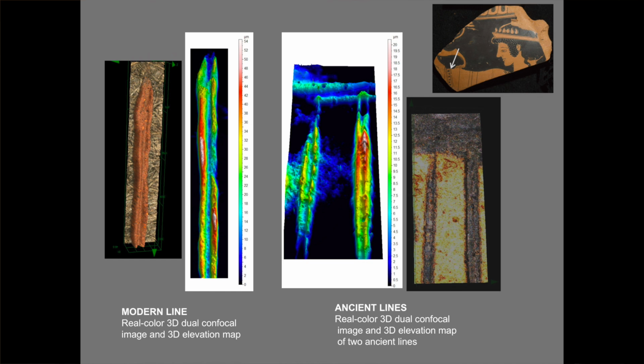I want to add that in our experiments we determined that a brush with a single hair could not have produced any of these lines because a brush of just one hair does not pick up enough medium to produce a line. 2 or more brush hairs are needed to physically pick up enough paint medium through the capillary action phenomenon to produce a line. When we examined the modern and ancient pulled lines with our 3D microscope, the resemblance between these lines was striking. The ancient ones and the modern ones.